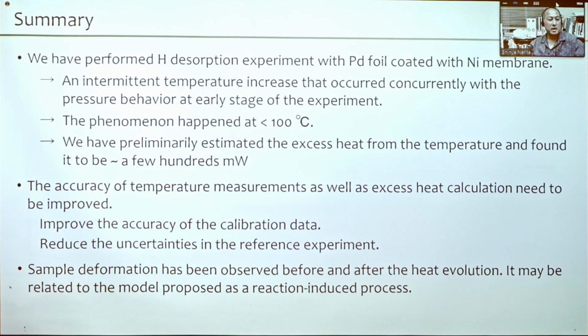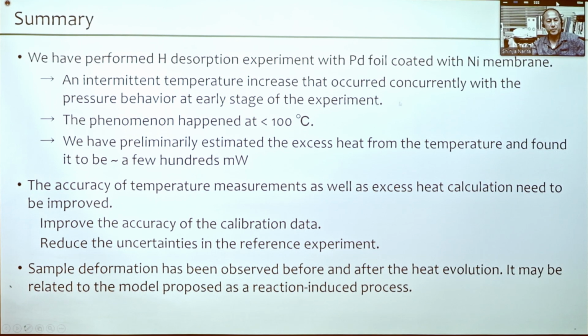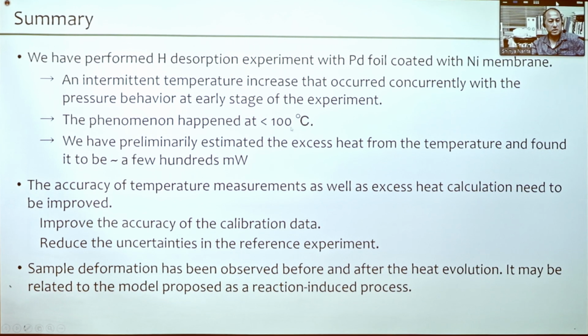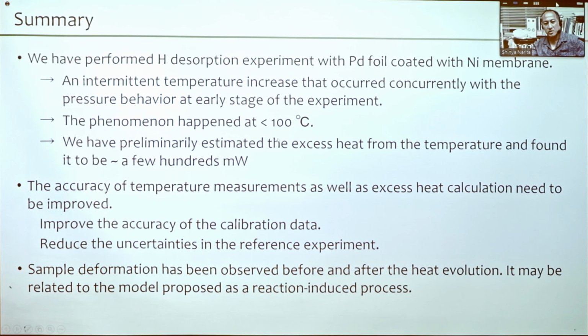Okay, in summary, we have performed a hydrogen desorption experiment with palladium foil coated with nickel membrane. We observed an intermittent temperature increase that occurred concurrently with the pressure behavior at the early stage of the experiment. The phenomena happened at low temperature, below 100 degrees Celsius, and we have preliminarily estimated the excess heat from the temperature and found it to be a few hundred milliwatts, but it is still preliminary, so we should consider carefully the ambiguity in the estimation.